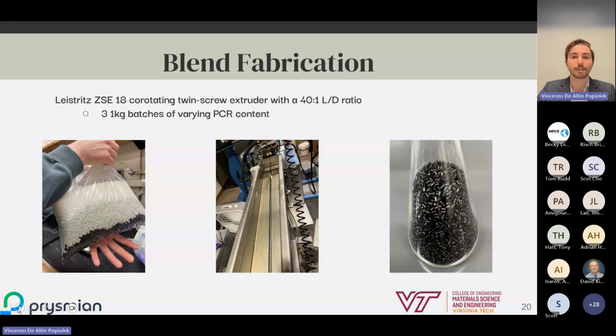Thanks to the Moore Lab in the chemistry department at Virginia Tech, we were able to gain access to a Leistritz ZSE 18 co-rotating twin screw extruder with a 40:1 L/D ratio. Using this, we fabricated 3 1-kilogram batches with those varying PCR contents.